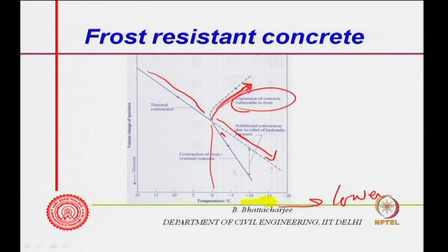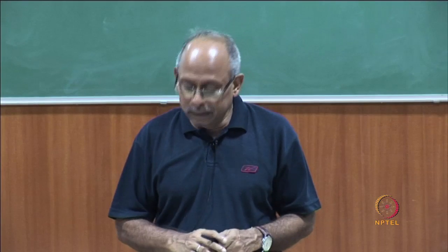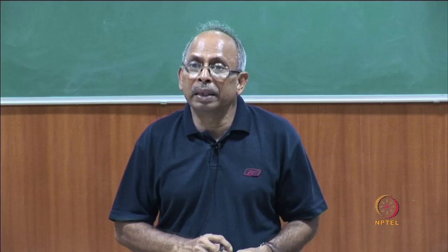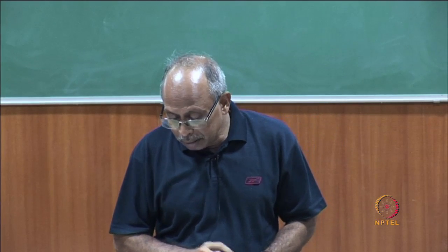While if I have air entrained concrete, the pressure is relieved, and as the pressure is relieved, the skeleton gets contracted because of the thermal contraction effect. Altogether there is a reduction in the volume, even more than thermal contraction. So air entrained concrete is not only frost resistant, it shows a reduction in the thermal contraction effect, but also further reduction in the volume of the whole system, because the pressure that would have been created hydraulically is released somewhere else, and the contraction is even more in this particular case.